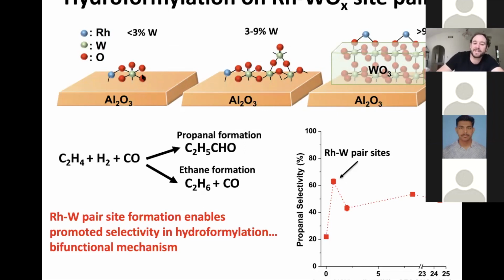And we have evidence that the chemistry here is occurring in a bifunctional nature, where ethylene binds here and CO binds here, and they react at the interface. So we can form pairs of sites on purpose that will allow us to have increased functionalities, which we just couldn't get out of clusters or metal particles.